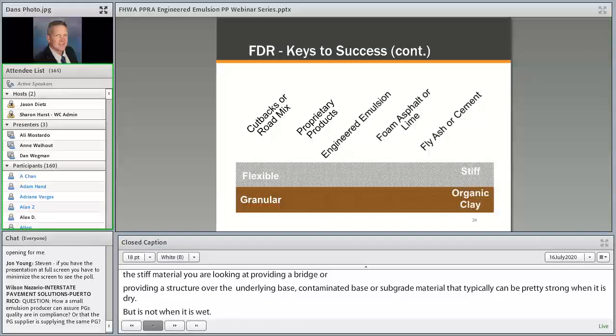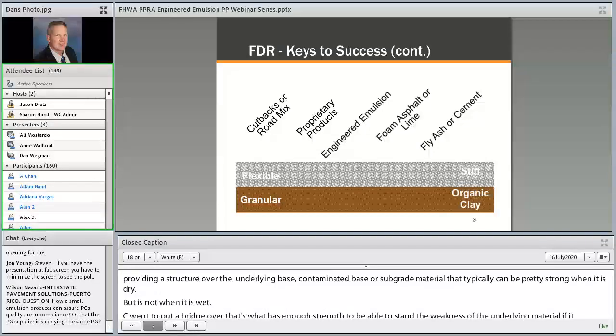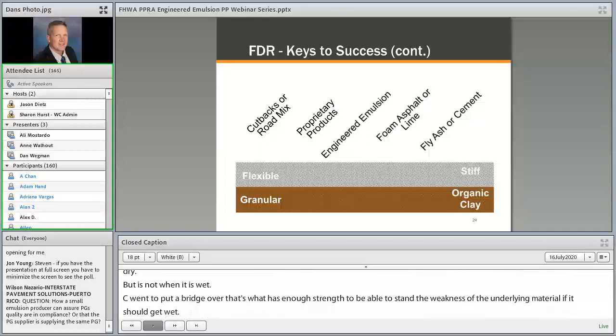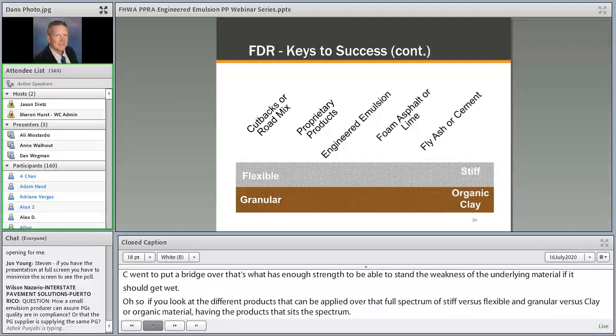And so if you look at the different products that can be applied over that full spectrum of stiff versus flexible and granular versus clay or organic material, I've put the products across that spectrum, with cutbacks or road mix material being to the far left. Those are very flexible materials that can be used, but in some cases, if you've got heavy loading, can be too soft or too flexible and can have rutting occur.